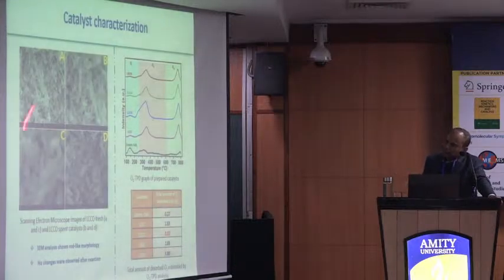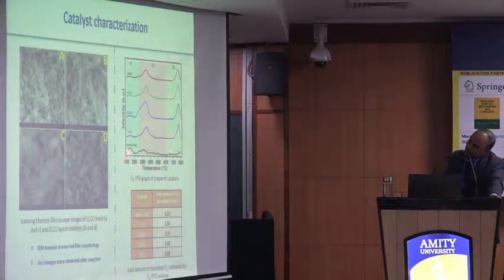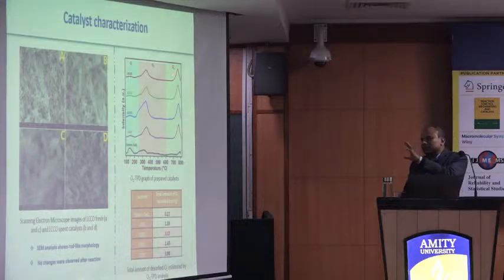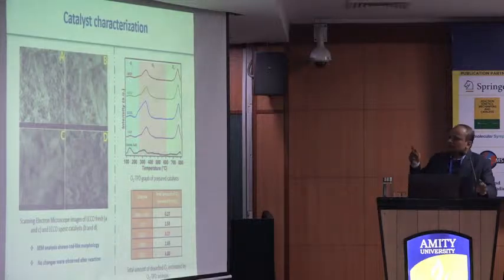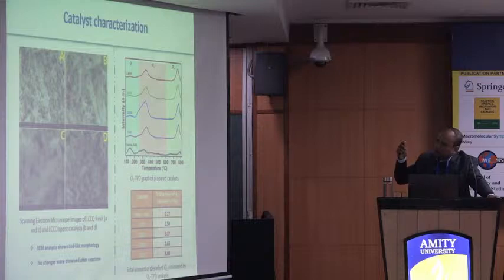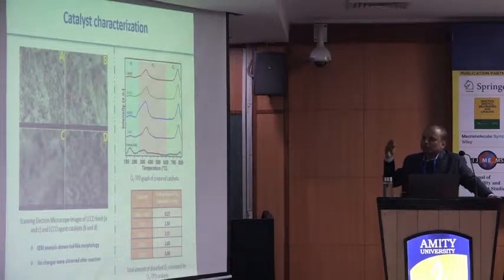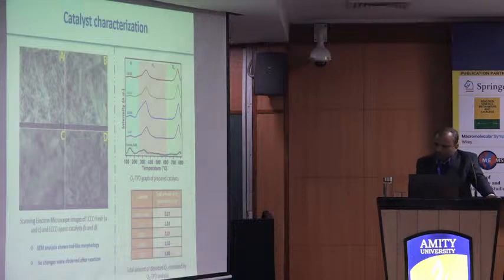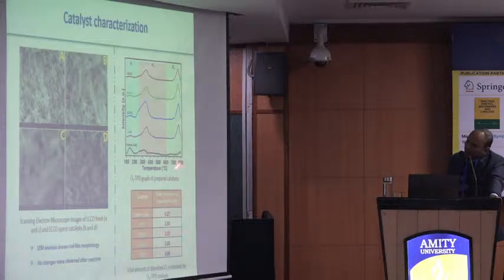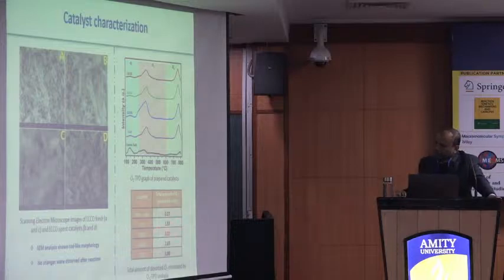This is the scanning electron microscope. We can see that rod-like morphology is present here, and this is the oxygen TPD. Interestingly, we got a peak in the moderate region, and we say this is the region where the oxygen vacancy, which we call superoxide species, is probably present in the catalyst. Also, calcium supported lanthanum ceria oxide is showing the maximum oxygen desorption peak, that is 3.37 cc per gram.